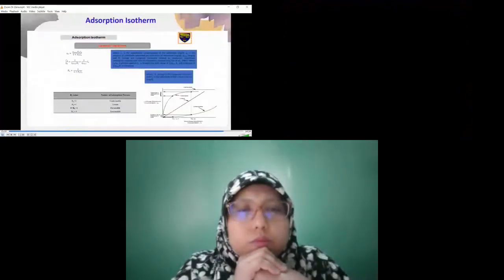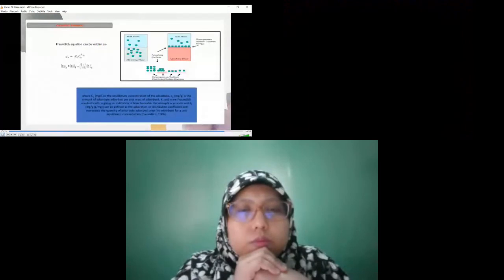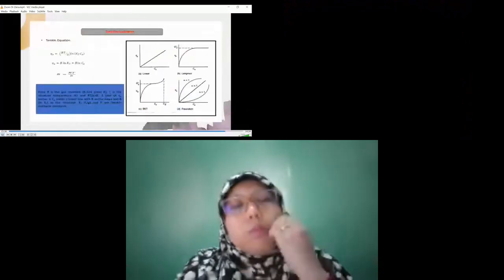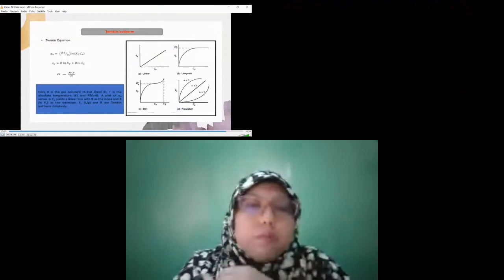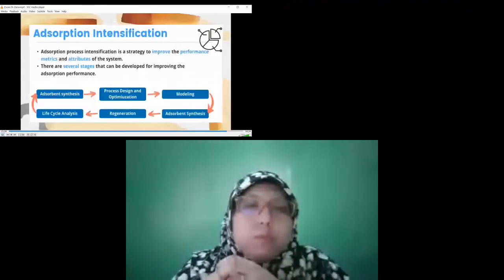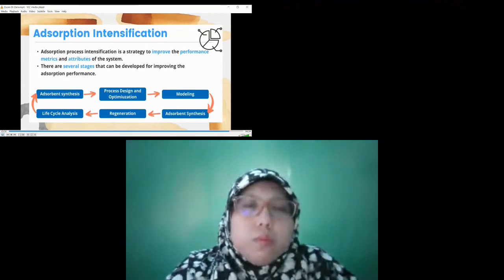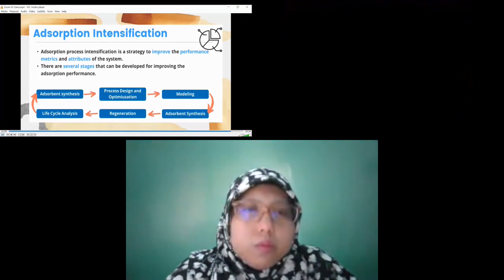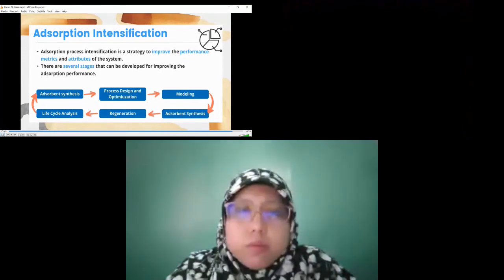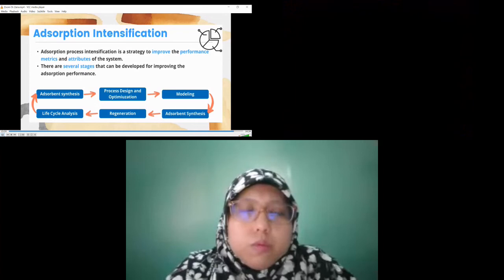This is the adsorption isotherm. Langmuir is checked for maximum monolayer adsorption capacity. Freundlich is checked for affinity factor, and Temkin is checked for the Ce and Qe relationship with temperature. So for the adsorption intensification process, we have to go for adsorbent synthesis, then process optimization, then modeling. After getting the optimum carbon, we have to go for adsorption tests, regenerate it, and analyze its life cycle, how we use the regenerated carbon. So this is the way we go for adsorption experiments by synthesizing structured carbon.